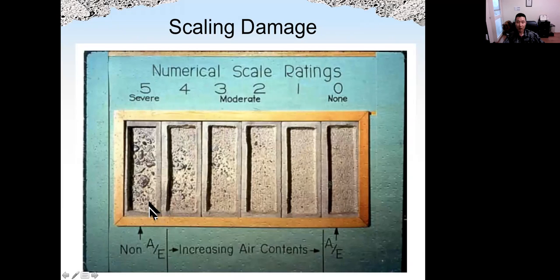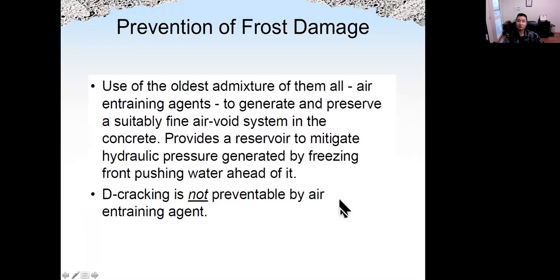And here shows how air entraining agent can reduce the scaling damage. So the same concrete with no air entraining agent, if we increase air content, the damage on the surface is reduced, as we can see clearly from here. So to reduce frost damage, we can use air entraining agent that will generate tiny isolated air bubbles, which are empty. So that will release the stress coming from the expansion in volume.